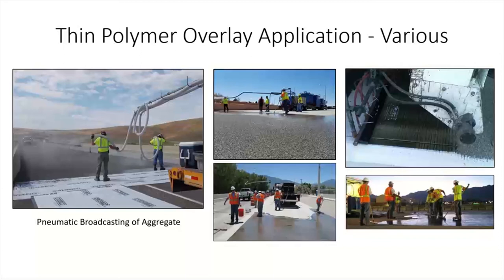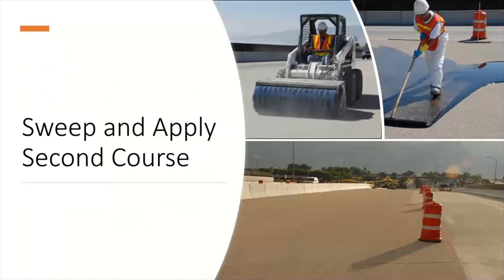Typically, you wouldn't want to pull out a big truck like that on a small project. Most of those applications with full automation are done on a high friction surface treatment, where some of the variables are more critical, and curves and things like that. After you're done with the first course, and when it's fully cured enough that you can get a sweeper, and there's various ways of sweeping, you sweep off the excess aggregate and you apply the resin binder again and you let it fully cure, sweep it again, and you can get traffic on it dependent upon the temperature. Temperature is a big factor, and we're going to talk about why making sure that the resin binder system is fully cured before you return it to traffic or before you even sweep off the aggregate on the first course.